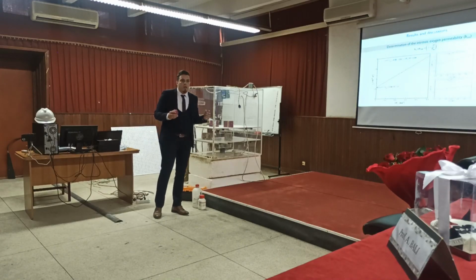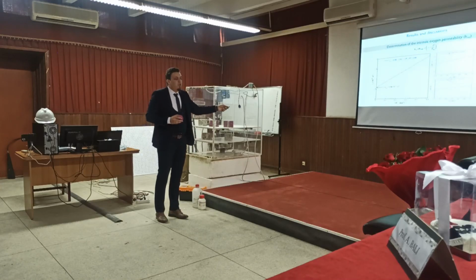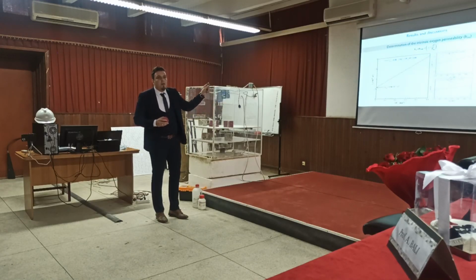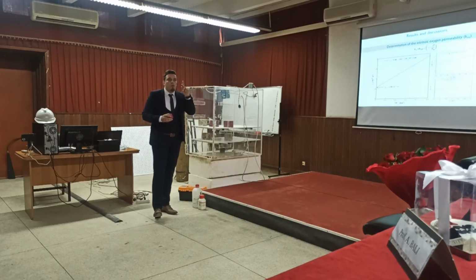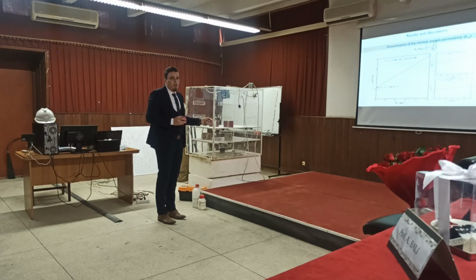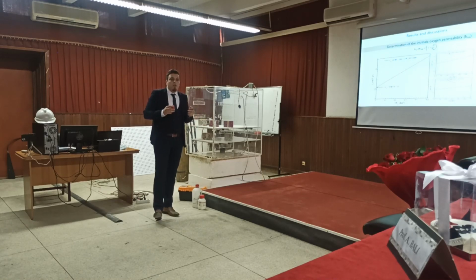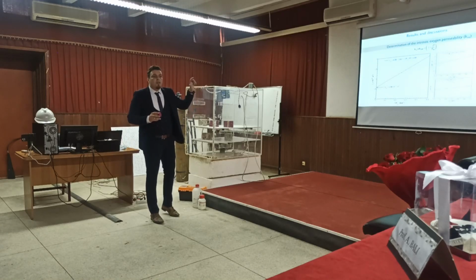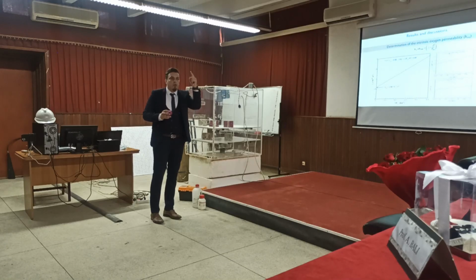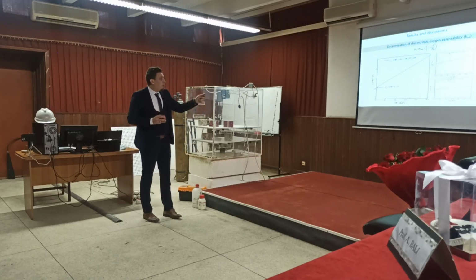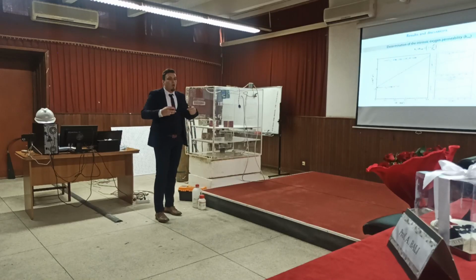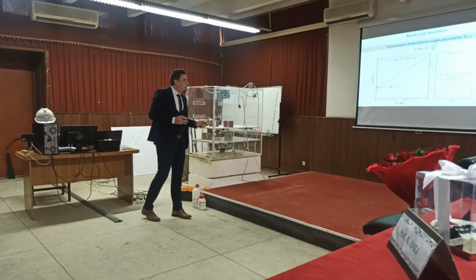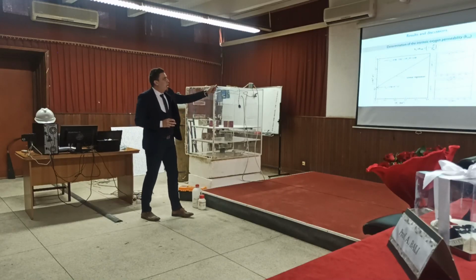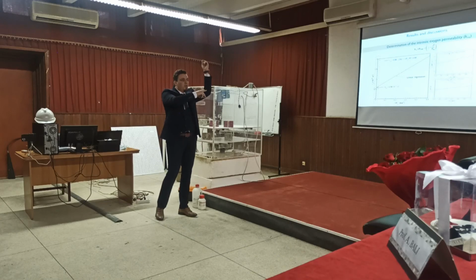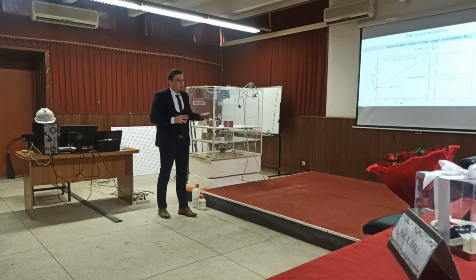Before plotting any figures and analyzing any results, we prefer to work with the intrinsic permeability rather than the apparent permeability. In order to obtain one value, we should plot 3 values of Ka. For the non-carbonated concrete and for the carbonated concrete, we can spend a day to have just one value of Ka. Imagine how much effort it takes to have just one value of K_int, which is the intrinsic permeability. So everything we will see is as a function of the intrinsic permeability. This is an example of how to obtain it: with linear regression, the intersection with the y-axis is the intrinsic permeability.